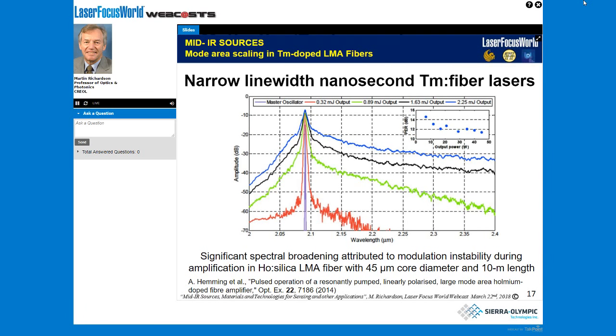The spectral characteristics of these fiber lasers can be controlled. Thulium has a broad bandwidth, as I've noticed before, and can be tuned all the way across that bandwidth. But likewise, narrow line widths can be achieved, or the lasers can be seeded with narrow line width sources, both for thulium and for holmium. And the power is driven up to the point where nonlinear modulation and instabilities start to broaden the spectrum. That, in principle, could be useful in some applications of the mid-IR, but in general is to be avoided.